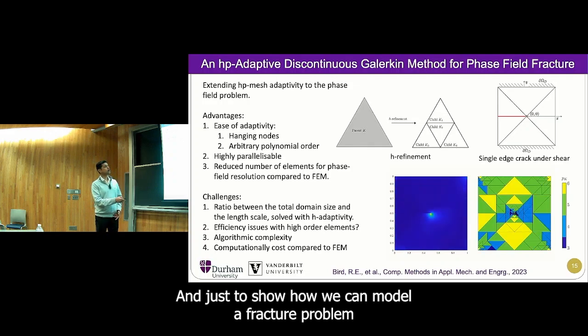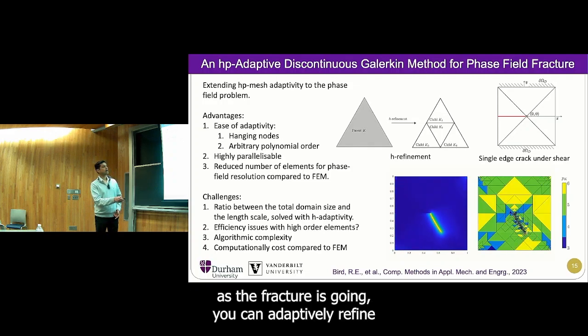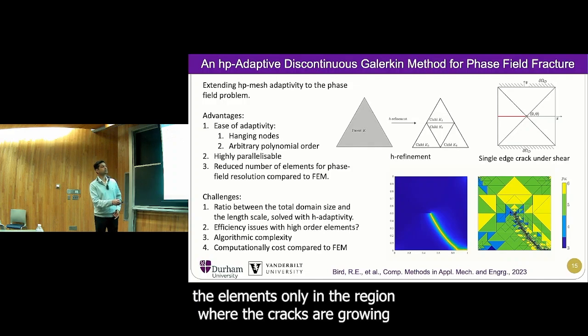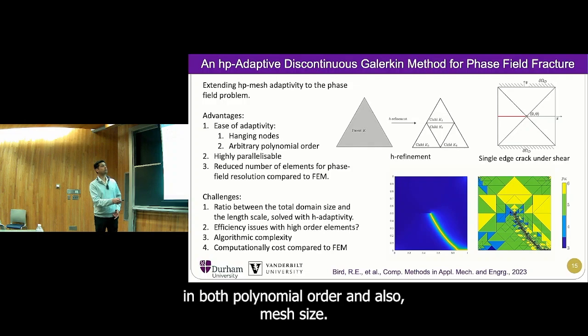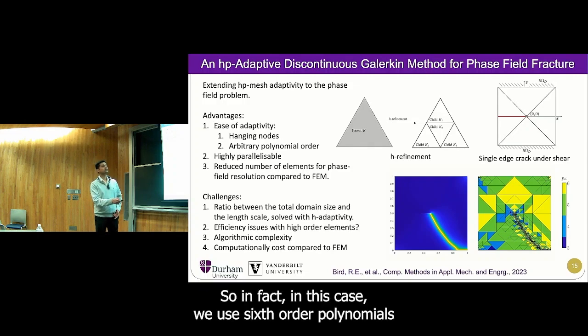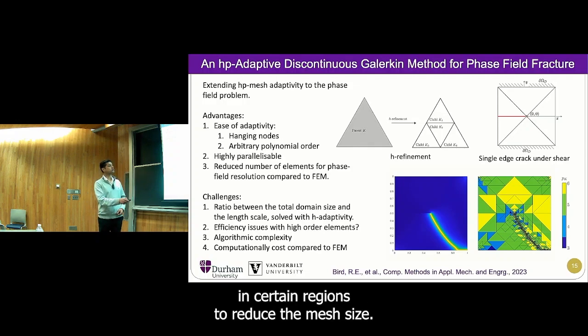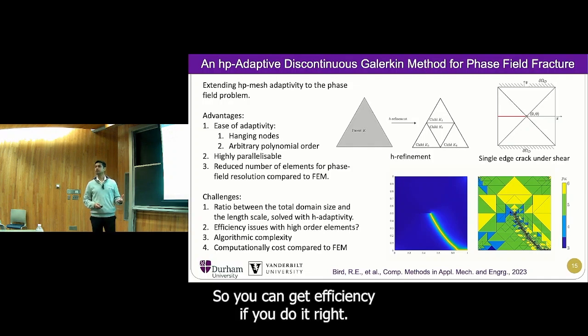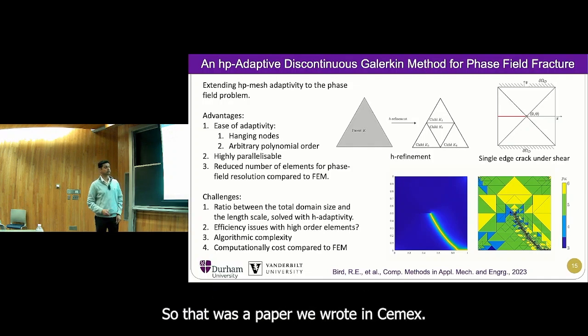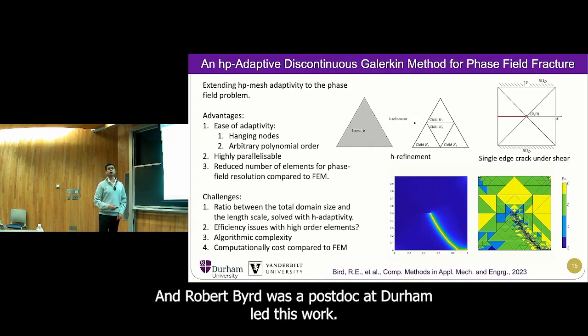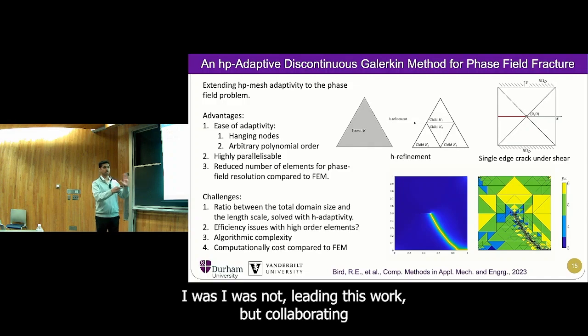And just to show how we can model a fracture problem, as the fracture is going, you can adaptively refine the elements only in the region where the cracks are growing, in both polynomial order and also mesh size. So in fact, in this case, we use 6th order polynomials in certain regions to reduce the mesh size. So you can get efficiency if you do it right. That was a paper we wrote in CompMech, and Robert Bird, who's a postdoc at Durham, led this work. I was not leading this work, but collaborating.